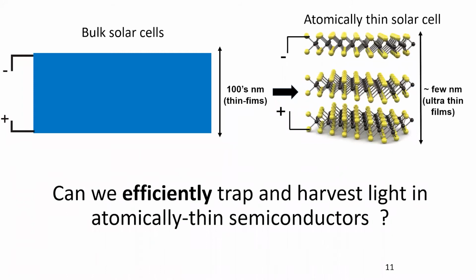And so the real challenge for us when we started thinking about this was: can you take the bulk solar cells that you would normally put in space and thin them down to an atomically thin solar cell while maintaining some kind of efficiency? I mean, you don't want the efficiency to be completely close to zero. It has to have a decent efficiency, and then it has to be very thin in order for the power per weight ratio to go up. And so the question that we had was, can you efficiently trap and harvest light in atomically thin semiconductors?